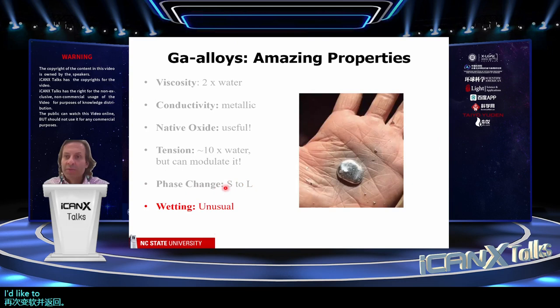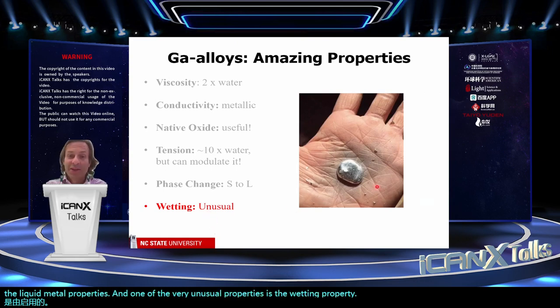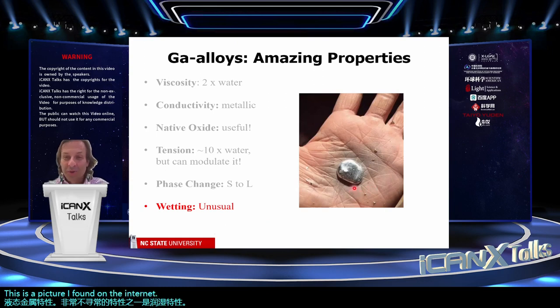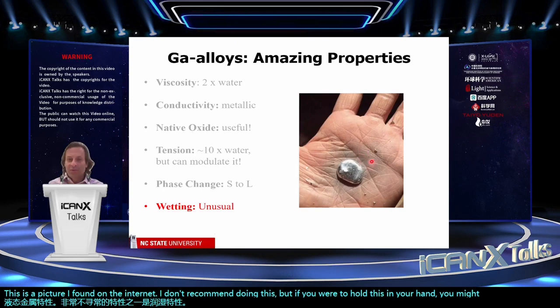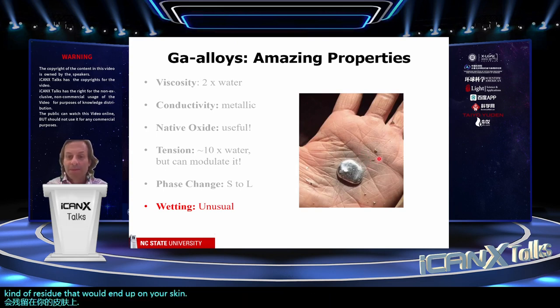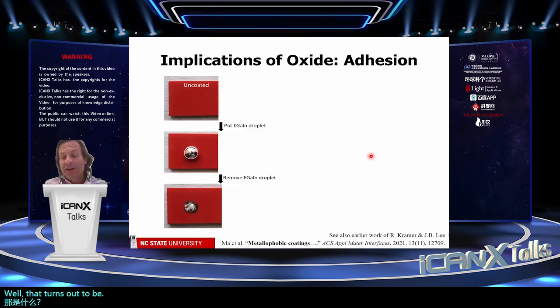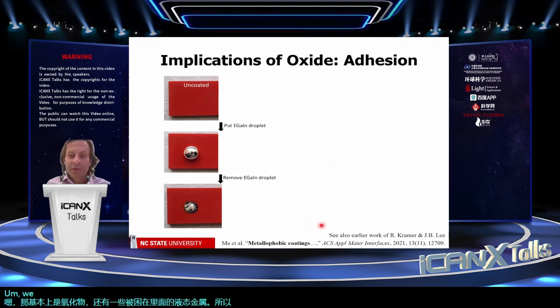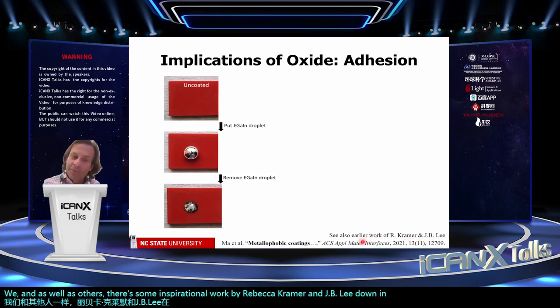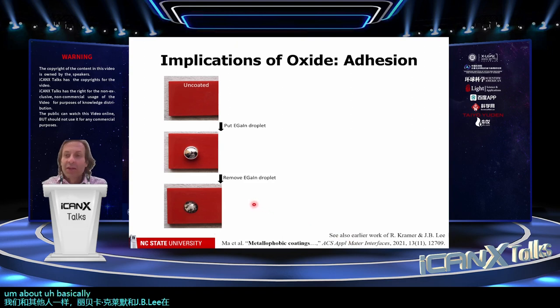I'd like to spend the rest of my time talking about some of the interesting fundamentals that are enabled by the liquid metal properties. One of the very unusual properties is the wetting properties. This is a picture I found on the internet. I don't recommend doing this, but if you were to hold this in your hand, you might notice that there's some kind of residue that would end up on your skin. So what is that? Well, that turns out to be basically oxide along with some liquid metal that gets trapped in there. And we, as well as others, with some inspirational work by Rebecca Kramer and JB Lee down in Dallas, are taking advantage of the oxide layer to either promote or avoid adhesion.